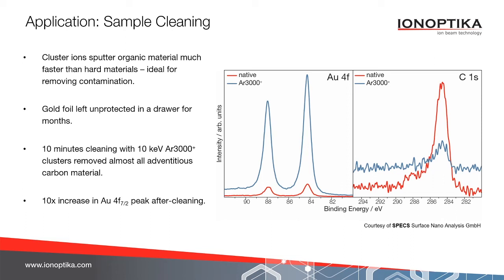The other main area that the GCIB 10S falls under is sample cleaning. As I mentioned, the damage done to hard materials as well as soft materials is minimal. However, the sputter rate is very different for organic material compared with hard materials. In most cases, it's approximately 10 times faster to sputter soft organic material than it is to sputter hard material.